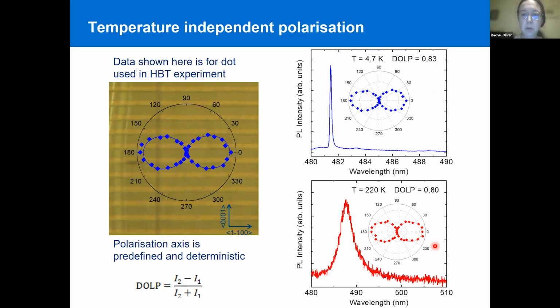I showed before that these dots emitted linearly polarized light. This data now on the polarization is from the same dot where I showed the Hanbury Brown and Twiss data. And again, we have highly polarized light. The degree of polarization here is 83%.